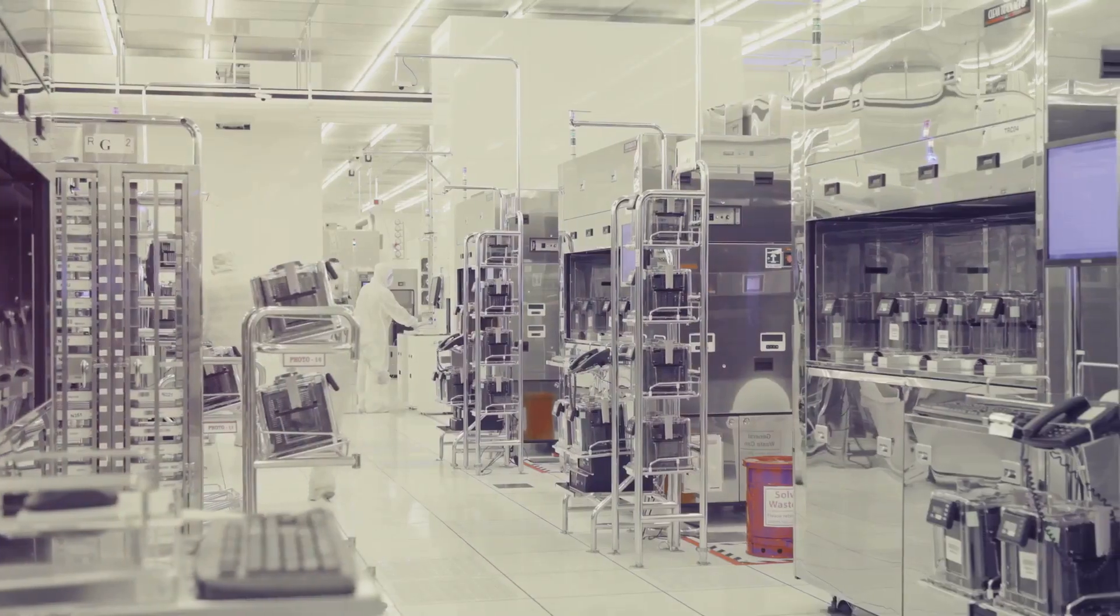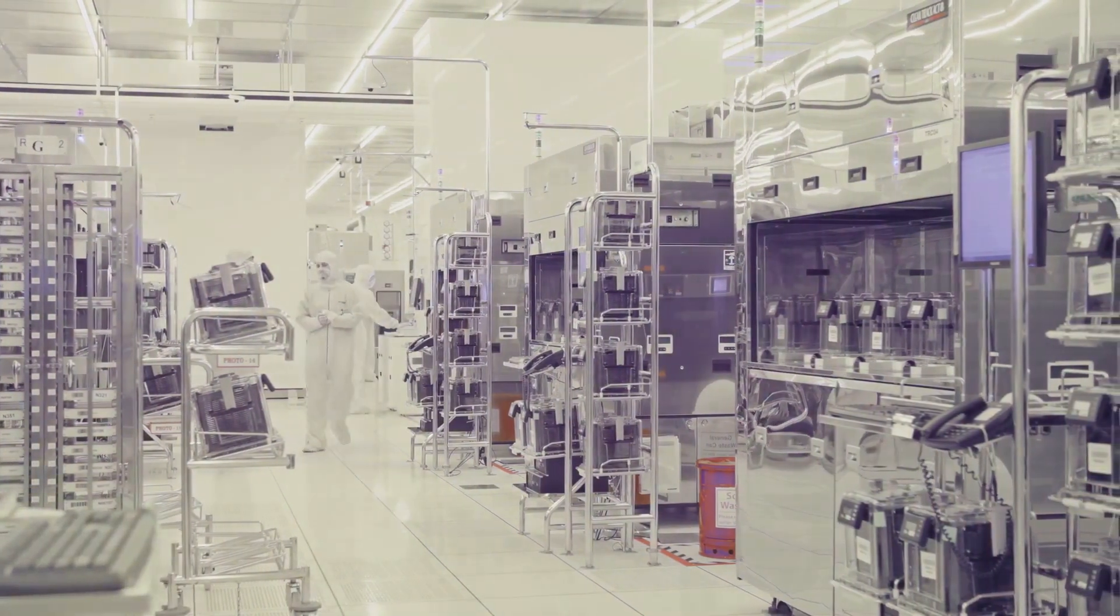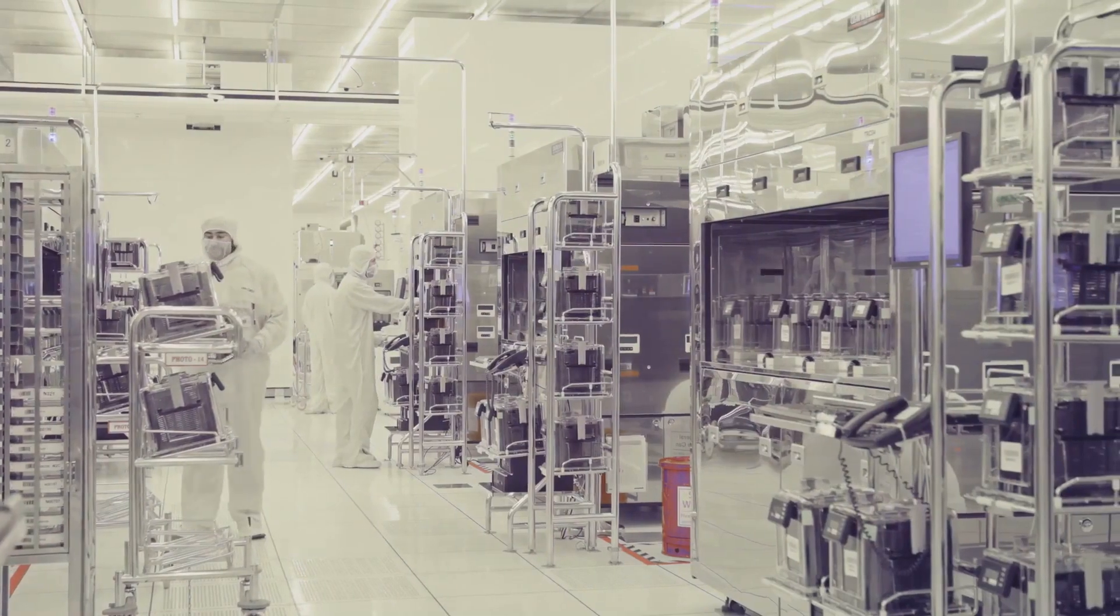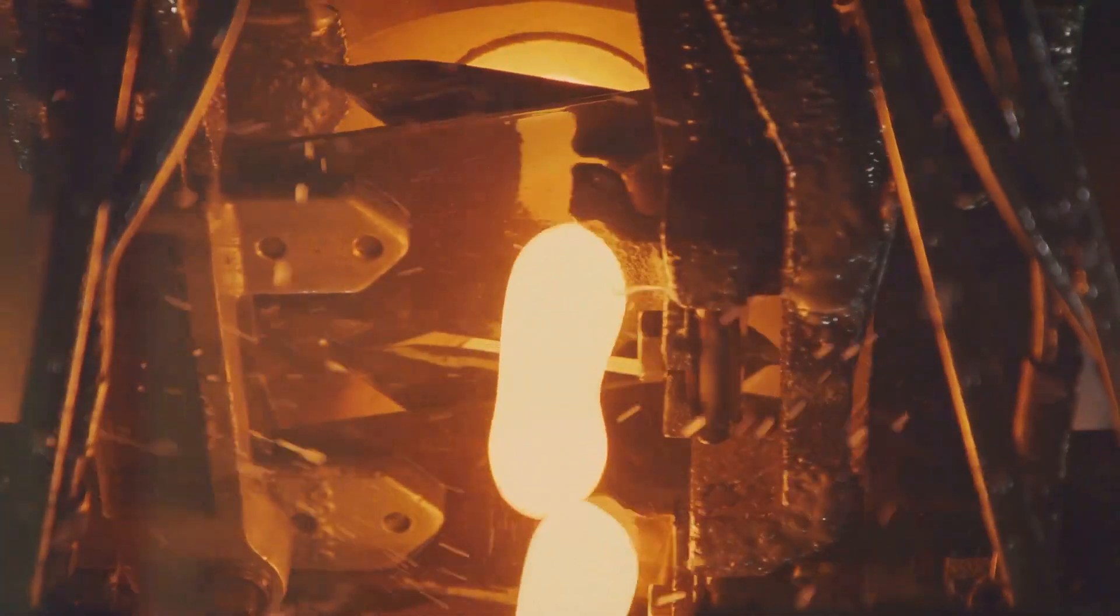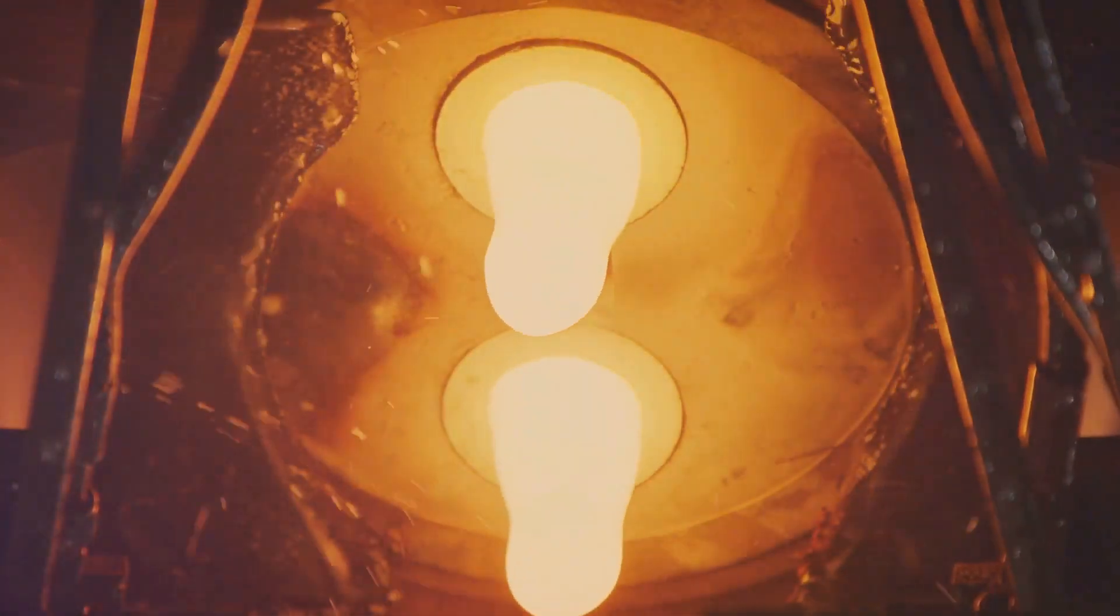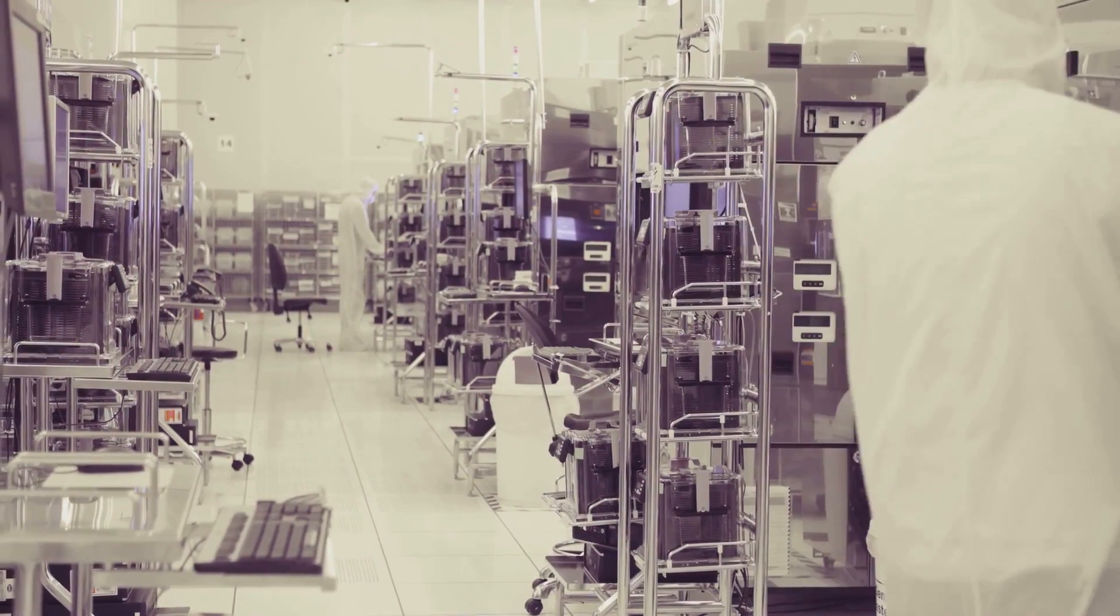We're talking about silicon that's so pure, it's over 99.9999% silicon. Now, this high purity polycrystalline silicon doesn't just melt on its own, it needs a lot of heat. The silicon is placed inside a quartz crucible, a vessel capable of withstanding incredibly high temperatures. We then crank up the heat to over 1,400 degrees Celsius. That's hotter than the surface of Venus, the hottest planet in our solar system.